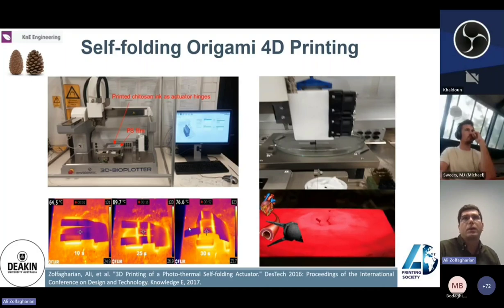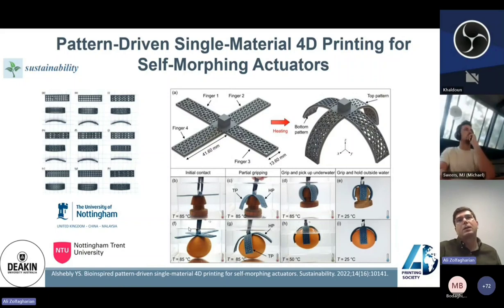And this was one of the running works in terms of the 4D printed origami that we could achieve. And then this work evolved so that recently, with our colleagues at the University of Nottingham and Nottingham Trent University, we came up with this idea of 4D printing of soft grippers. As you could see, using the 3D printing processing parameters, like the velocity of the nozzle or how fast you do the 3D printing at different layers, and also the different patterns that you could use, in order to achieve the bending in the soft actuator or soft grippers.